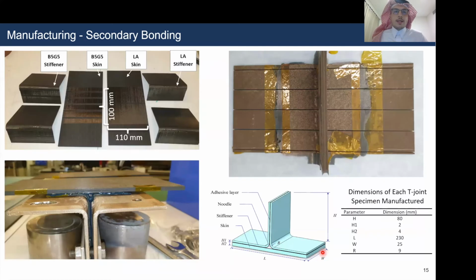And then once the cured skin and the cured stiffener were produced, they were cut, and then they experienced the laser treatment. So these are images of the skins and the stiffeners after the treatment. We can notice here that there is an alternation between a dark region, which is the LA, and a lighter region, which is the low fluence laser cleaning LC. The laser patterning was also applied to the stiffener. And on the right, we have the pure or uniform LA pretreatment.